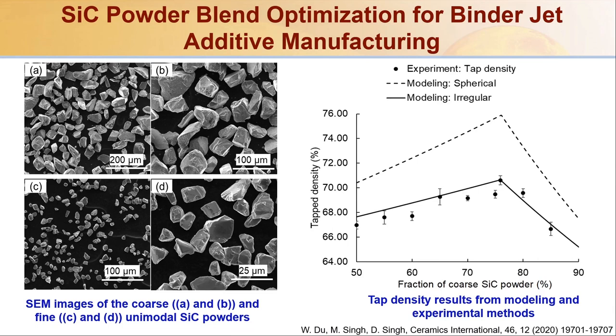But I would like to show you some SEM images of coarse and fine-grained silicon carbide powders. And based on those models, we basically try to mix these powders in different ratios. If you look on the right side, there is, of course, the tap density result from modeling and experimental methods. The tap density according to these two models, which are using a spherical model and an irregular shape model, is fairly consistent, especially using the irregular shapes.